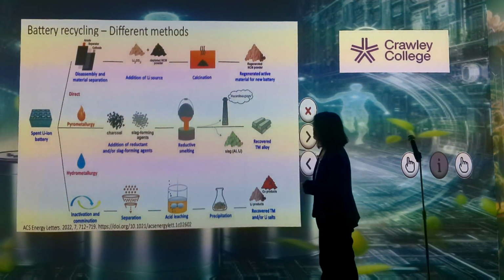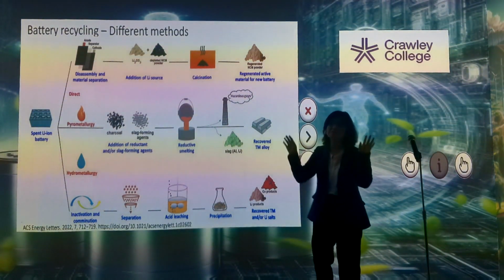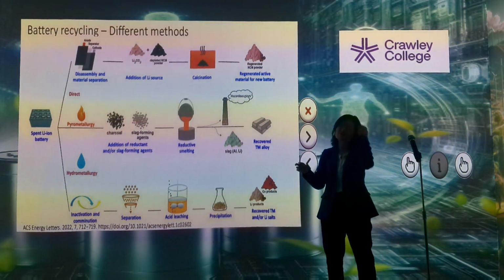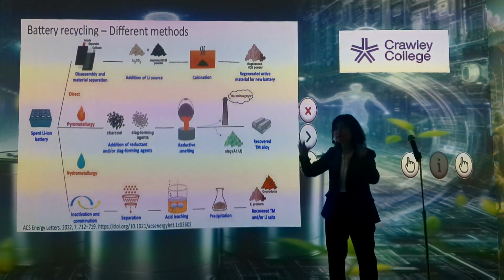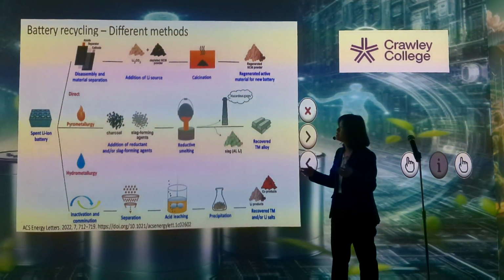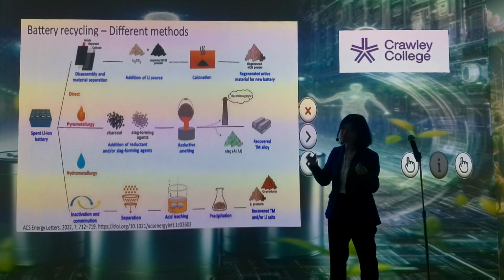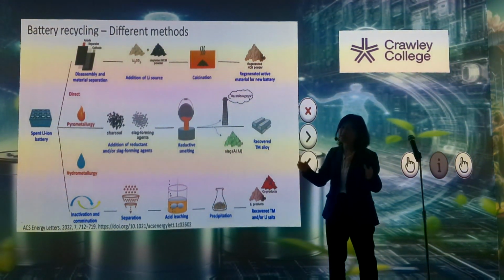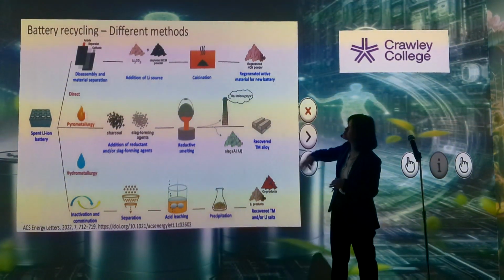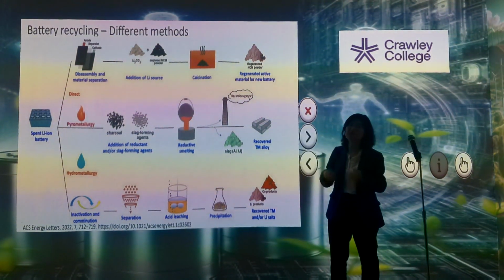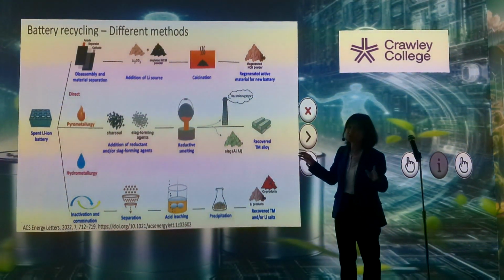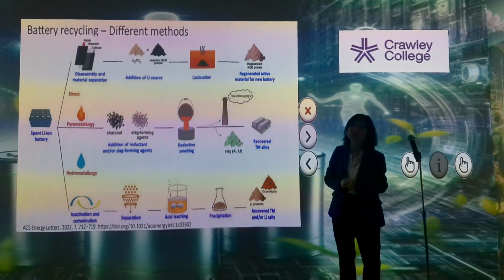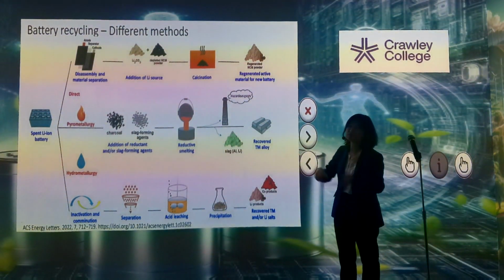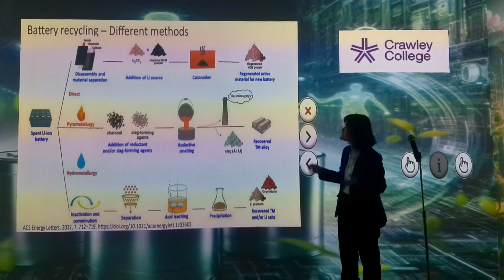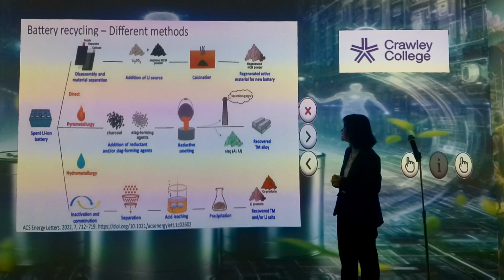Another method is called the direct recycling method. This is when we have cathode materials and there's some damage to the cathode material. So the value lies mostly with the cathode materials. There's some crack maybe in the cathode materials, or the cathode material maybe lost some element, and you use some chemicals to repair that cathode material. So it happens at relatively mild condition, and therefore you can achieve very good recovery efficiency and also an environmentally more benign, more environmentally friendly approach.